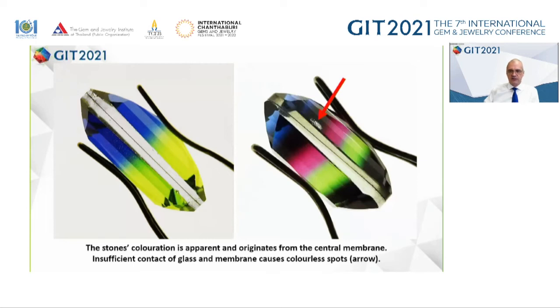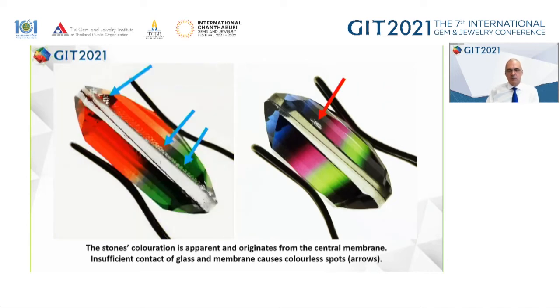There's of course a problem sometimes due to the quick production. So these halves are just stuck together, and if the tape is not really attached to the glass, as you can see here marked by an arrow, then we see these spots that come from insufficient contact, and sometimes it's really a problem. Almost half of the stone here is affected by this. You cannot see it when you look from the top, but from the side, this is quite well seen, and I would say it affects about a third of all stones that we saw on the market.